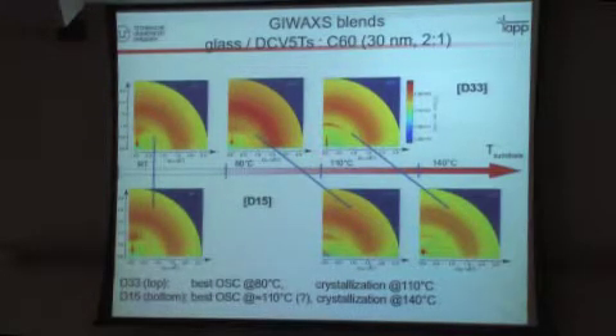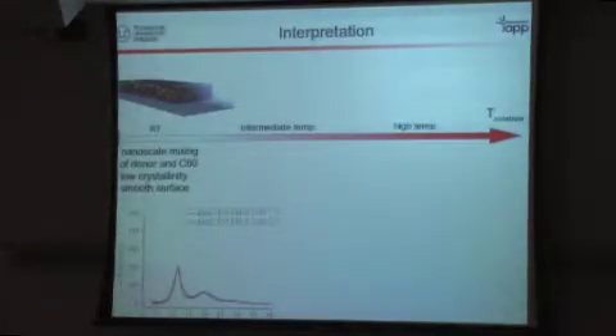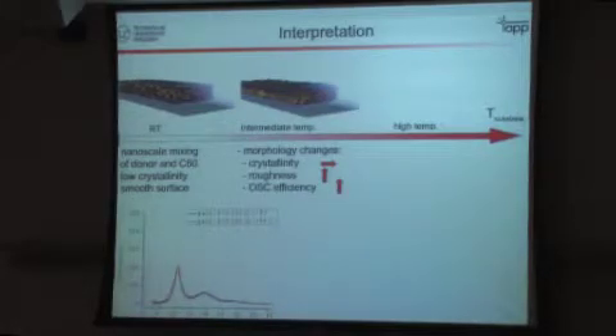And the problem is that compound 1 is already at a temperature which is critical for organic solar cells. So we simply didn't go to that temperature when we made the devices because of diffusion effects. And the whole morphology development as a function of temperature turned out to be rather complex. At room temperature, you have very small domains with low crystallinity. And when you go to higher temperatures, the domains grow larger. The crystallinity actually wasn't much higher, so the main effect of the better reflexes was a larger domain size.